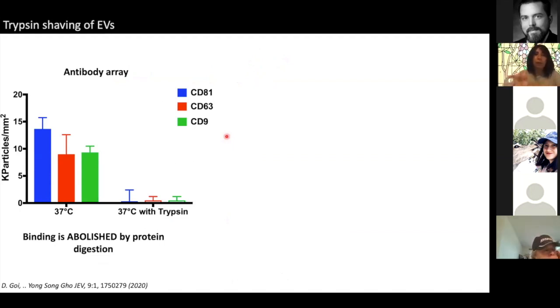And what we did is an experiment of trypsin shaving or trypsin digestion of the proteins on the surface of extracellular vesicles. So we took a sample of EVs that were isolated from human serum by ultracentrifugation, and we subjected the sample to 2 protocols. We incubated at 37 degrees for 6 hours without or with trypsin. And as expected, on an antibody array where we have immobilized CD81, CD63, and CD9, the binding of the vesicles is abolished by the protein digestion. We do not have any binding due to trypsin digestion.